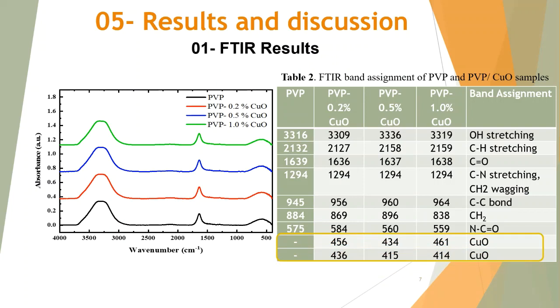This figure presents the FTIR absorption spectra of pure PVP and PVP doped with different concentrations of copper oxide nanoparticles. As we can see from the figure and table, the principal bands and functional groups associated with PVP are seen in the absorption spectra. However, the band assignment of pure PVP and PVP copper oxide nanocomposite solutions was obtained in this table, and it's clear from the table that the appearance of the copper oxide stretching vibration in the region above 400 cm-1 confirms the formation of hydrogen bonding between copper oxide and PVP and the formation of the nanocomposites.